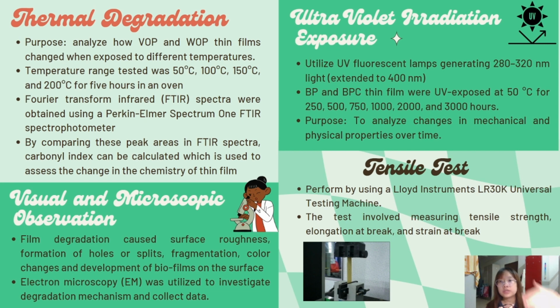So the temperature in this testing was 50, 100, 150 and 200 degrees Celsius for 5 hours in an oven. By comparing this peak area in the FTIR spectra, the carbonyl index can be calculated, which is used to assess the change in the chemistry of the thin film.